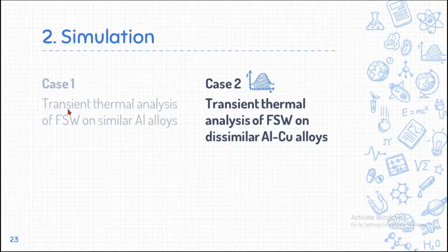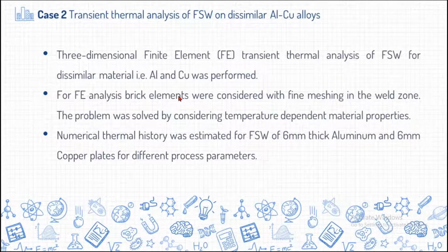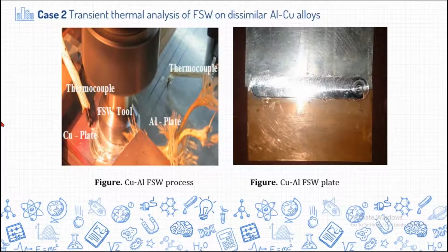So in this simulation case study, case one speaks about similar aluminum alloys, but case two is the transient thermal analysis of friction stir welding on dissimilar aluminum and copper alloys. This 3D FE analysis was performed on dissimilar aluminum and copper, with brick elements considered, and with fine meshing at the center of the welding and gradually incremental meshing away from the center of the welding. We applied the same technique I explained previously for the initial and final boundary conditions, and followed the same procedure for dissimilar aluminum alloys also.